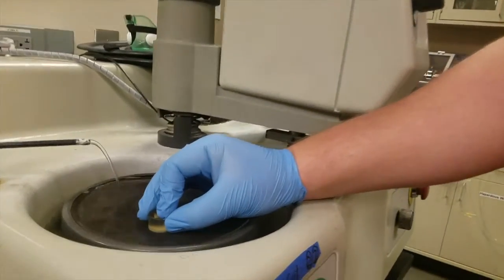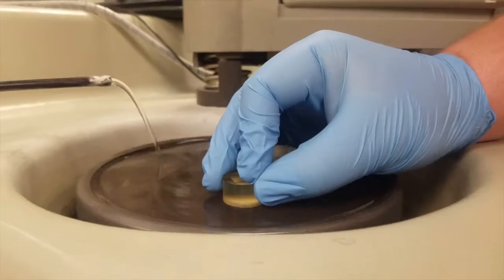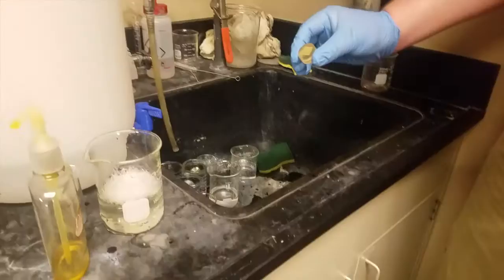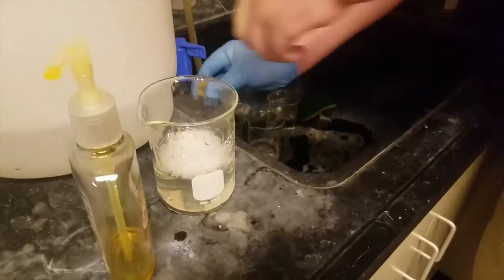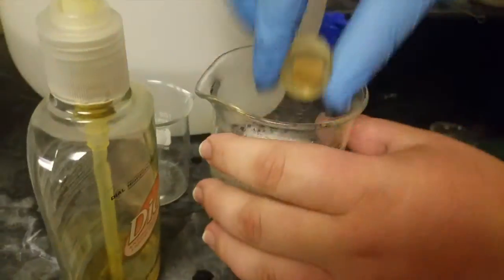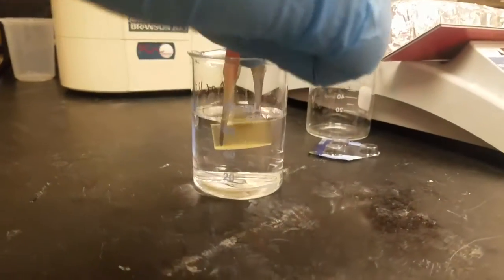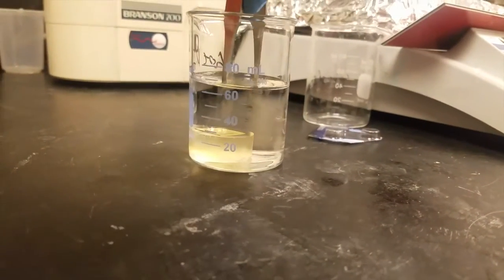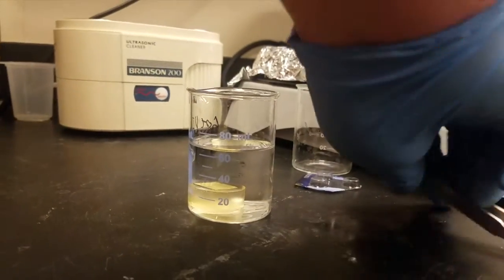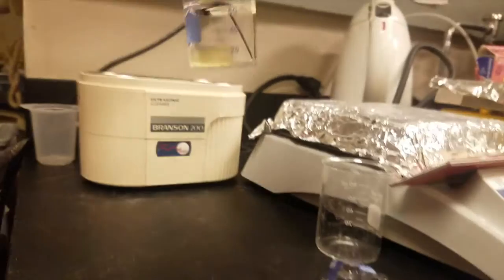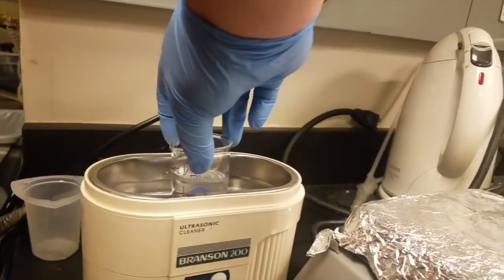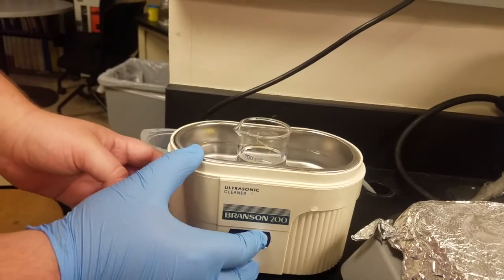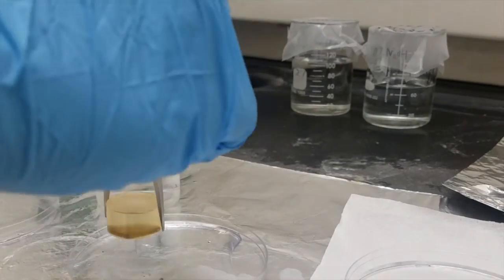The following polishing steps should take about 2 to 5 minutes each. Make sure to thoroughly clean the samples with soap water and isopropyl alcohol between polishing steps. However, after polishing with the 1 micron white label polishing paper with green lube and after polishing with the P-cloth with colloidal silica, make sure to sonicate the samples in clean isopropyl alcohol for 5 minutes to thoroughly clean the sample.